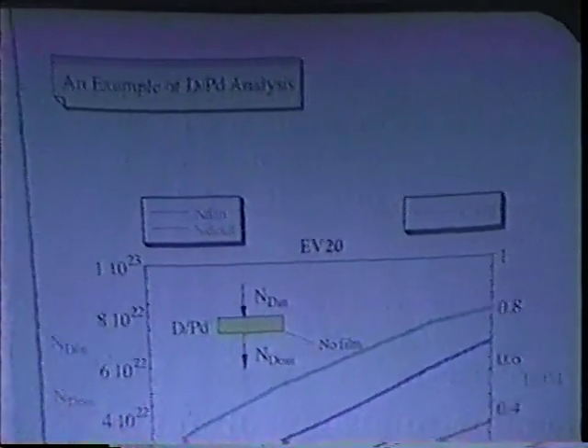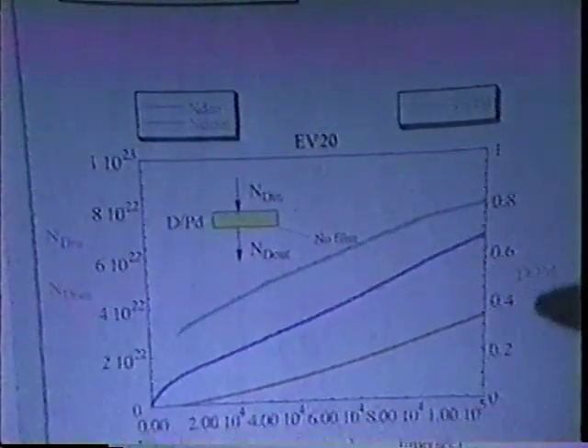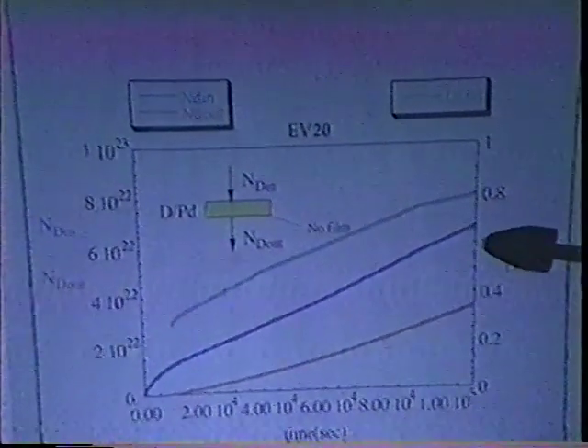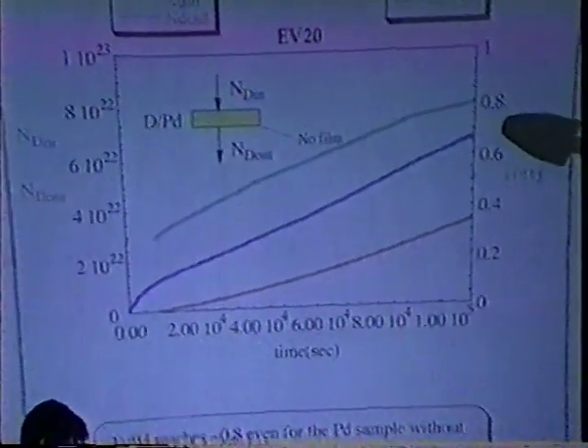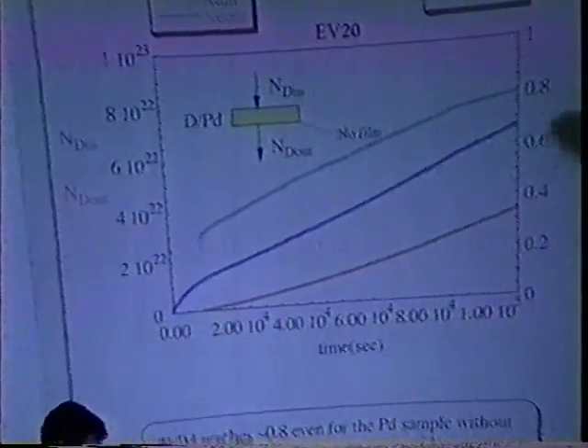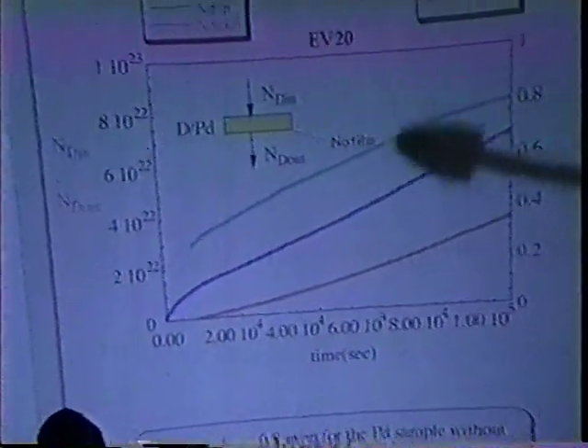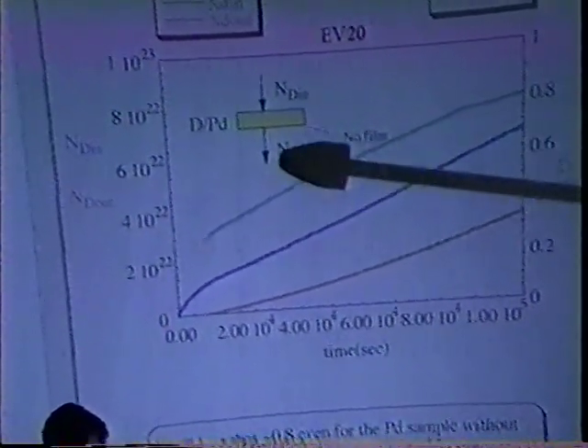Here is an example of D/Pd analysis. In this case, the palladium sample has no film on it. In this view graph, the blue line means the number of deuterons absorbed into the palladium, the red line means the number of deuterons released out from the palladium, and the green line means the D/Pd ratio. As we can see, the D/Pd ratio reaches about 0.8 even for the palladium sample without surface modification on the vacuum side.